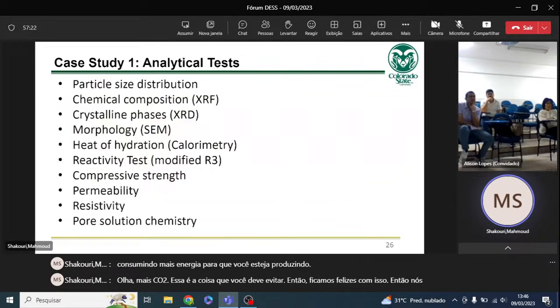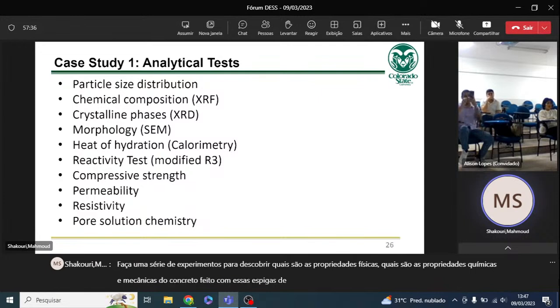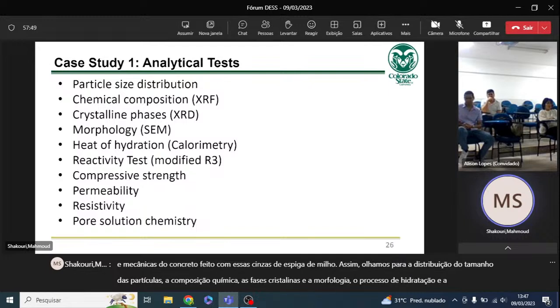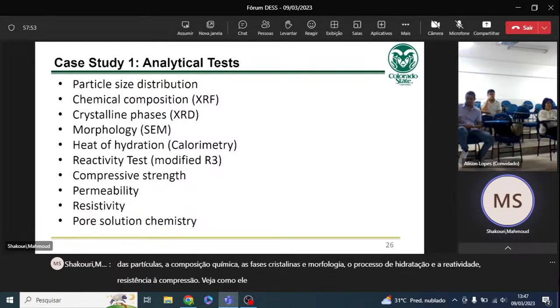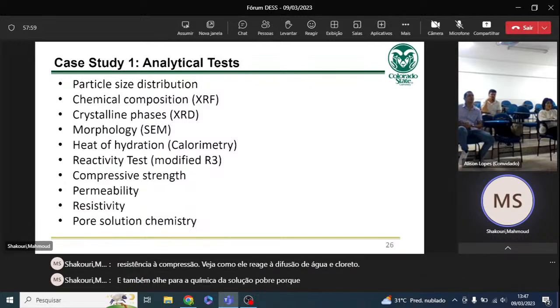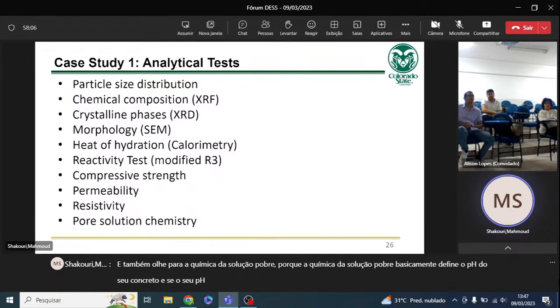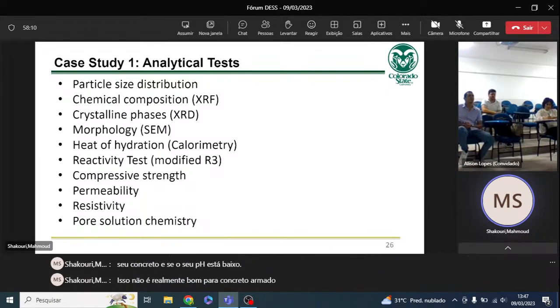So we used this and we did a series of experiments to find out what are the physical, chemical and mechanical properties of concrete made with this corncob ash. So we look at particle size distribution, chemical composition, the crystalline phases, morphology, the hydration process, the reactivity, compressive strengths, see how it reacts to the diffusion of water and chlorides, and also look at the pore solution chemistry, because pore solution chemistry basically defines the pH of your concrete, and if your pH is down, that's not really good for reinforced concrete because it may promote corrosion.